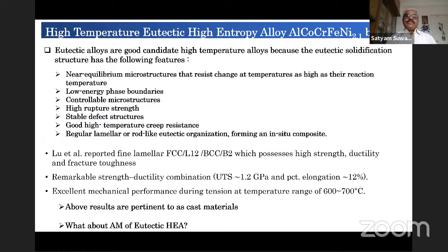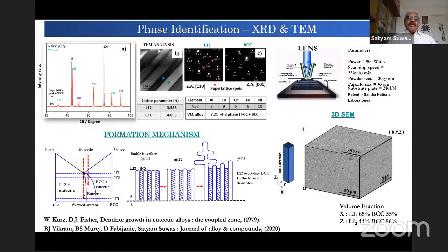Now, just before I close, I just wanted to give a glimpse of our work on high entropy alloys, because the tone was set by Professor Kim in the previous presentation. We worked on eutectic high temperature, high entropy alloys, which are supposed to be potential candidates for replacing some of the super alloys that we have mentioned. And we indeed worked on this well-established high entropy alloy, aluminum, cobalt, chromium, iron, and nickel 2.1. And we did this by additive manufacturing, by following all these methods. And because of the process attributes, we got this lamellar plus dendritic structure in a eutectic form.